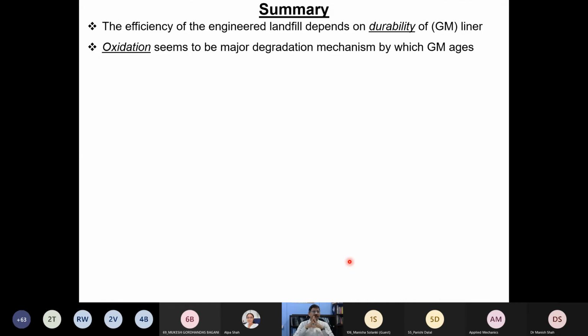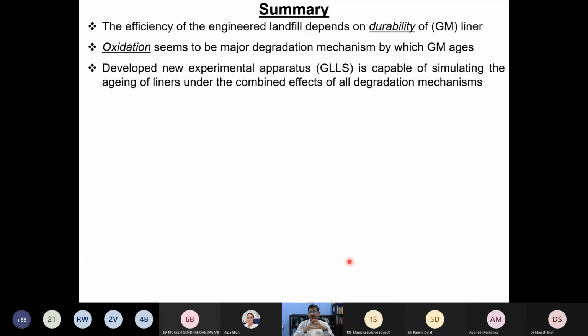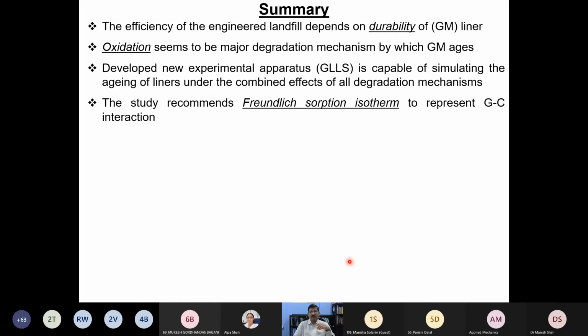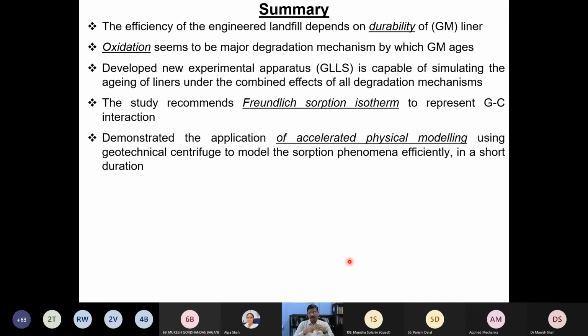We know that the efficacy of any engineered landfill primarily depends on the durability of the geomembrane liner. And oxidation seems to be one of the major mechanisms. We have also developed a unique apparatus called GLLS, which is capable of simulating the liner aging by considering the combined effect of all possible mechanisms. We have also shown very clearly through this presentation that the Freundlich sorption isotherm is very good to represent the geomembrane-contaminant interaction, particularly for heavy metals.